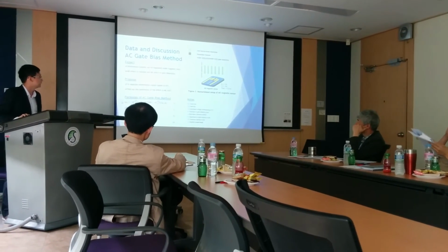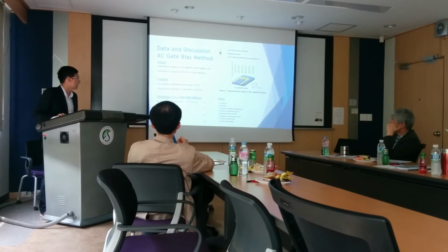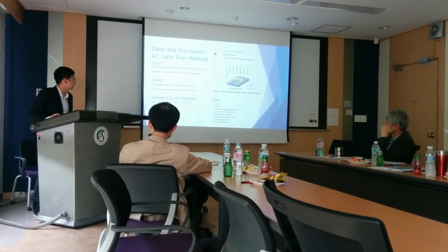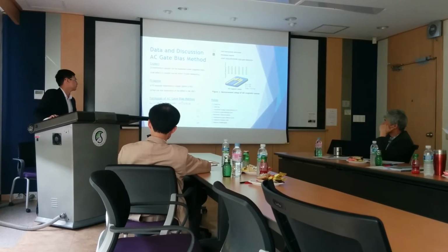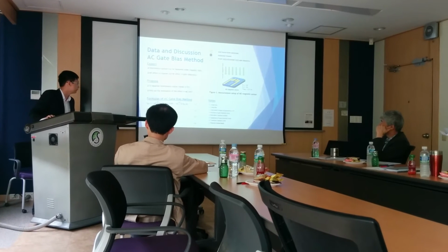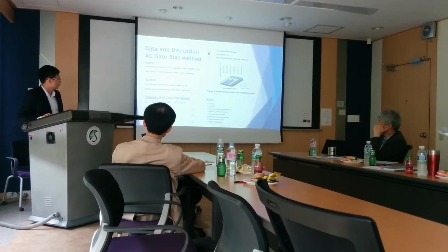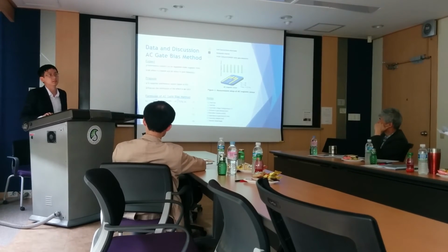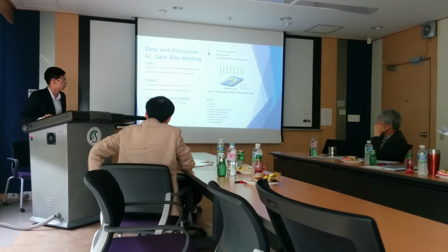From formula 1, this is the total current response, the amplitude current response from formula 2, and the mean current response from formula 3. To calculate the equivalent voltage in the piezoelectric material, we form the ratio of the mean current response and the amplitude current response, and we achieve it in formula 4.